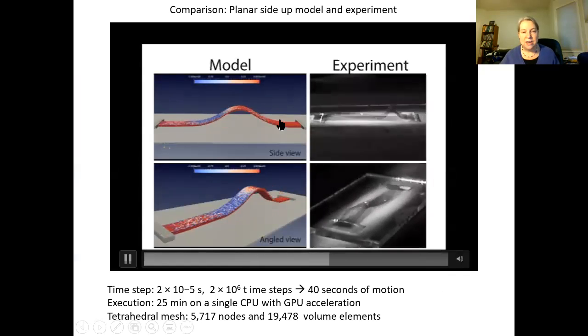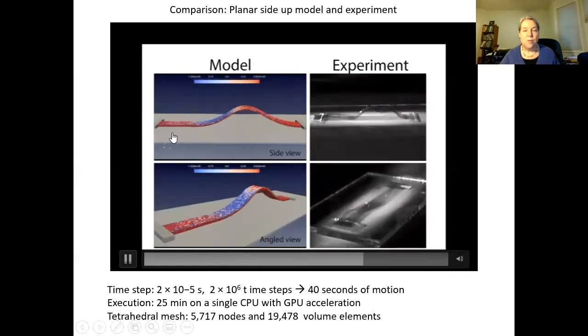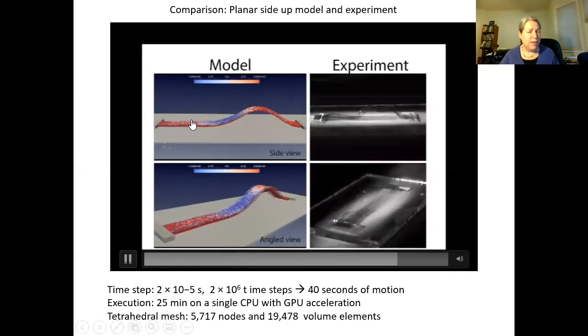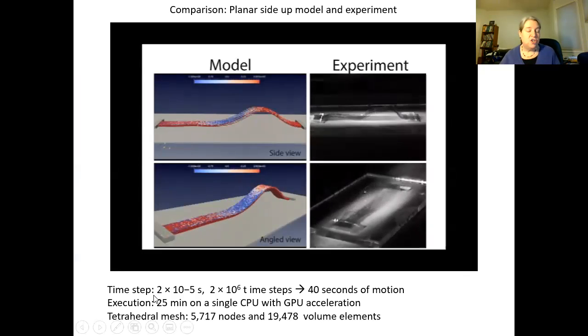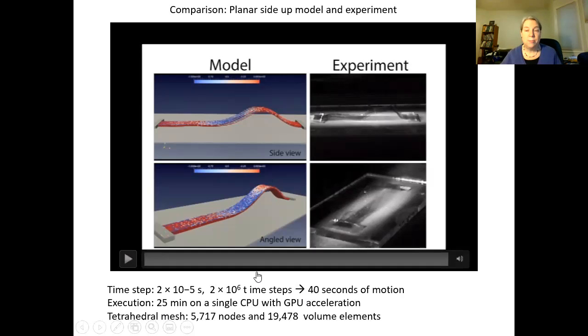In this one, the bump does manage to annihilate, but you can see the wave motion is driven by light exposure on the left side. And the waves are moving away from the light source, just from the point of view of what we were modeling in the simulation. Like I said, this is not a molecular simulation. This is at the lab scale. We modeled 40 seconds of motion, and the model ran in 25 minutes on a single CPU that had GPU acceleration and multiple cores. This was a simple simulation, a tetrahedral mesh with less than 6,000 nodes and just under 20,000 volume elements that are tetrahedral in shape.